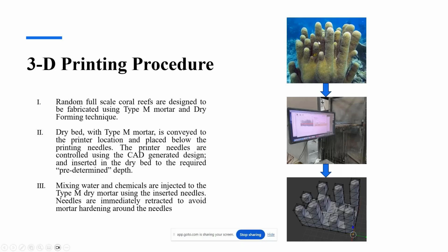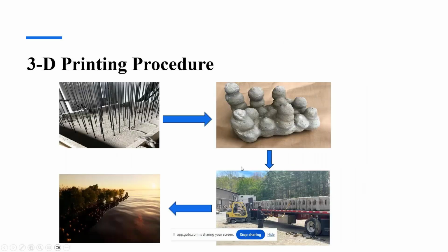So basically here that shows a picture of how the injection is distributed along the dry bed of our cementitious material, or the cement and the supplementary cementitious material, or the cement plus polymers, before dipping our straws. So this is basically the procedure. This is a dry bed, the straws being dipped in, and then this generates this type of shape, and this is loaded on trucks, and basically it is thrown at shallow water.